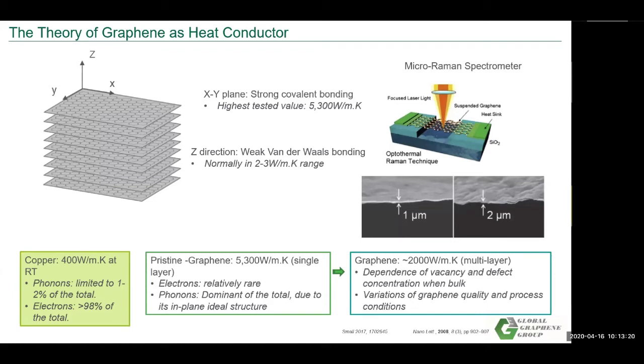But theoretical is one value, and actual practical use is another. When we use graphene, we have to consider the vacancies, the defects, and also the grain boundaries of graphene. When we connect all the graphene together, we normally get at best 2,000 watts per meter per K. People would expect 5,000 watts per meter per K, but in actuality we can get as close as 2,000 watts per meter per K.